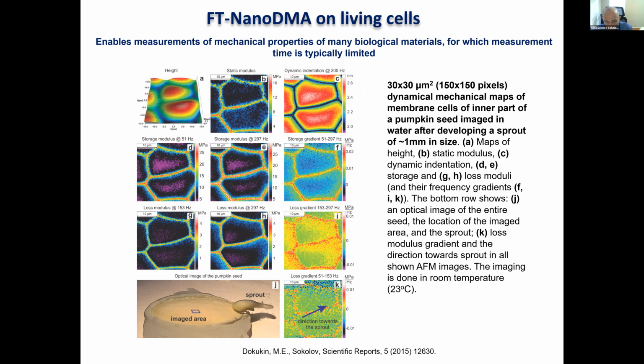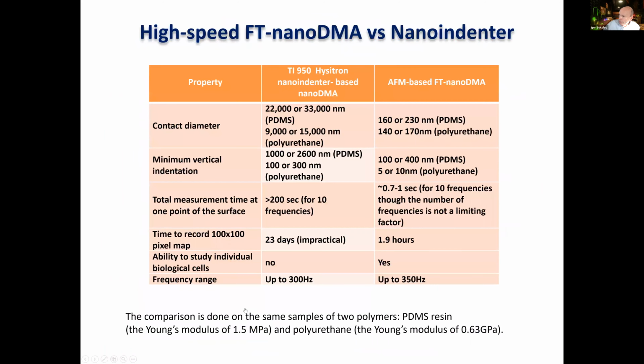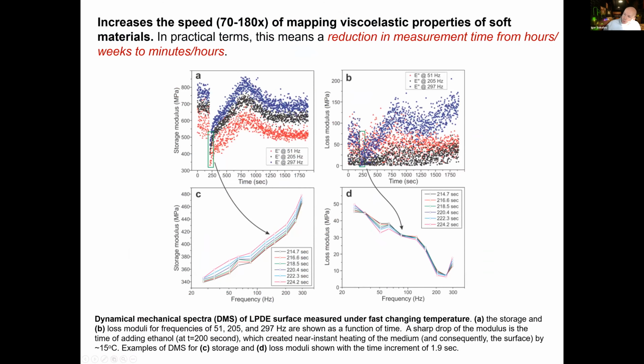The question is, can FT-nanoDMA work with samples in liquids and in variable temperature? Oh yeah, that's what I showed. In liquids, well, this sprout was growing in liquid, and also when we changed temperature, that sample is a piece of polymer approximately an inch in size and about 2-3 millimeters thick, completely covered with water, and then we added ethanol.